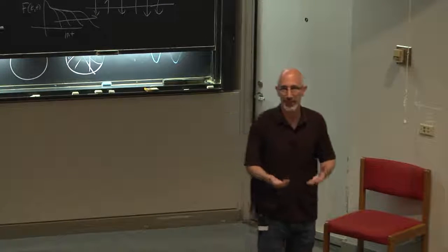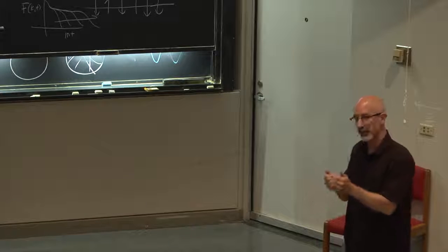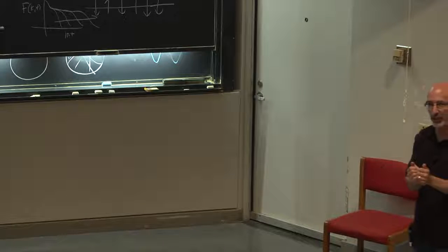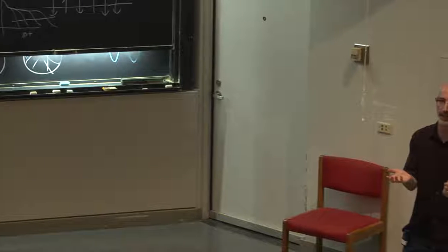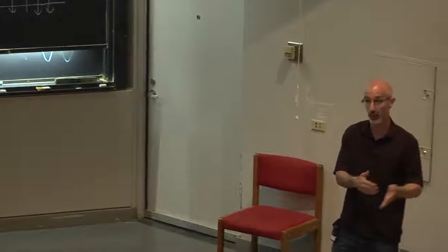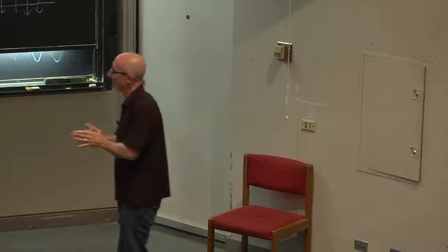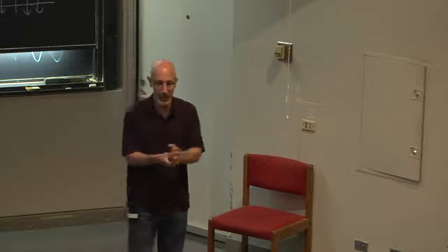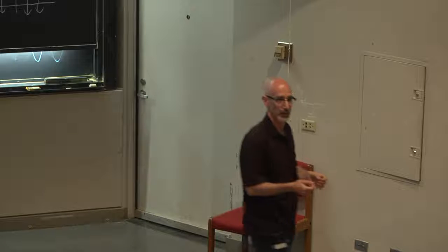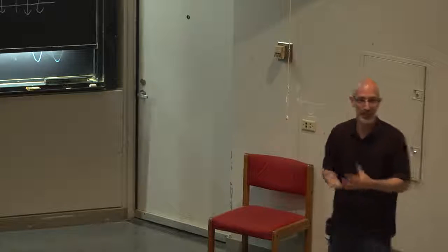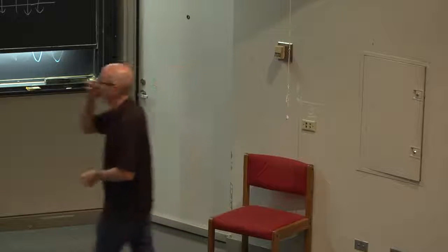So what this suggests is that even in 3 dimensions, there is a distinction between the fluctuations that give rise to Stokes-Einstein violation and the fluctuations that give rise to the growth of chi-4, and that maybe, in some aspect of the dynamical heterogeneity, we shouldn't necessarily only focus on the hopping-like motion. The hopping-like motion is the motion that we would associate most with Stokes-Einstein violation, but maybe we're not focusing on the things that aren't moving, right, which is the viscosity, and that's the important thing here. And I think that's really interesting.